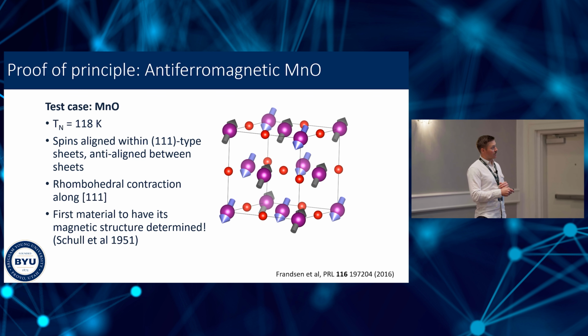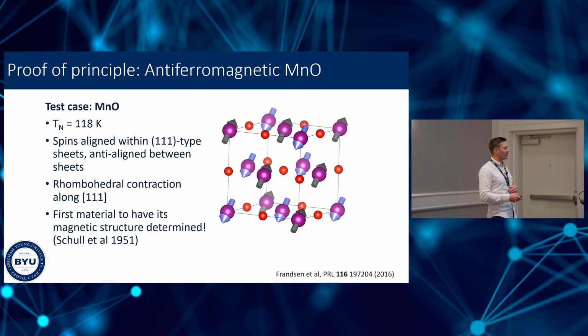It undergoes a long-range magnetic transition below 118 Kelvin. So below that temperature, we have this long-range antiferromagnetic order where the spins within shared 1-1-1 type planes are aligned with each other, but between alternating planes, the magnetization is reversed. Okay, so it's an overall antiferromagnetic structure.